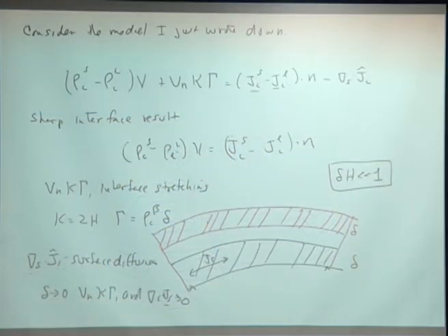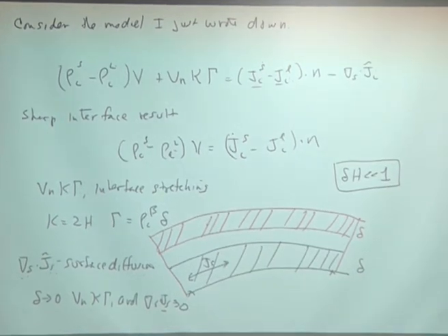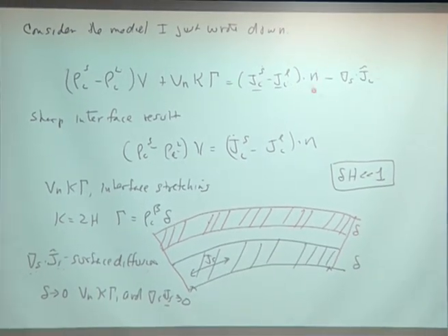And if you look in the literature, there's a lot of work on this. And in fact, you want to use the asymptotics where interface thickness times h is much, much less than 1. And then what people do is they change these evolution equations in order to knock out these terms. And so one of the ways of doing this, you'll see in the solidification community, is by Karma, and they put in what's called an anti-trapping term.